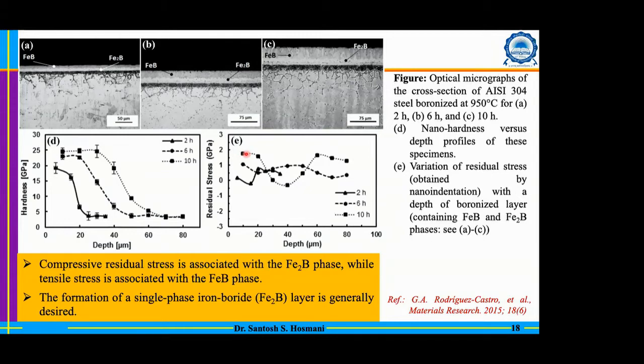As well as that, these two layers have different crystal structures and different coefficients of thermal expansion, and most likely there will be very weak adhesion between the FeB and Fe2B layers. That means there is a possibility that the FeB will be detached during operation. So that possibility is most likely there. And apart from that, the nature of this stress is very much dependent on your process parameters.